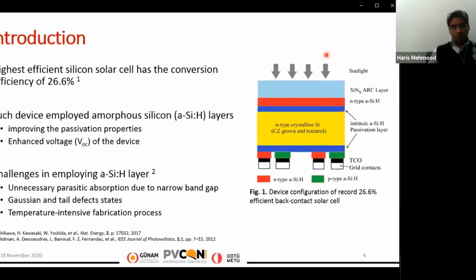This means that the front surface of this device receives the full coverage of the sunlight. So this type of solar cell has a higher short circuit current density of more than 40 milliampere per centimeter squared. However, there are various challenges associated with this state-of-the-art device, such that it is expensive to produce commercially because of the complex lithography requirements, as well as challenges associated with the doped amorphous silicon layer. Because of the low band gap of amorphous silicon, it tends to induce unnecessary parasitic absorption within the device. Similarly, there are Gaussian and tail defects present within the film that contribute to an increase in recombination centers. And of course, a temperature-intensive fabrication process would be required to fabricate the amorphous silicon layer.